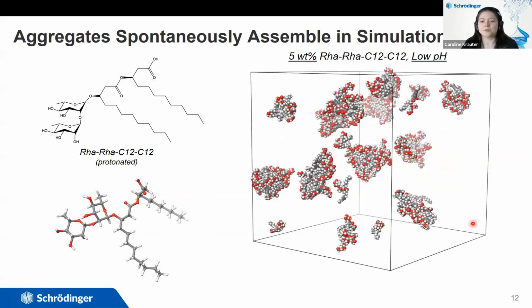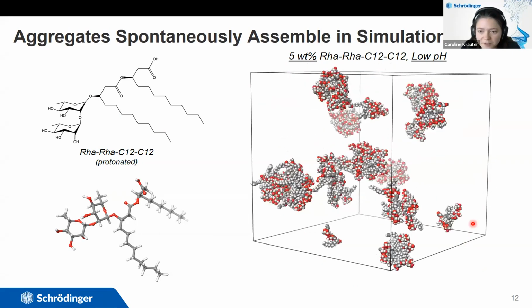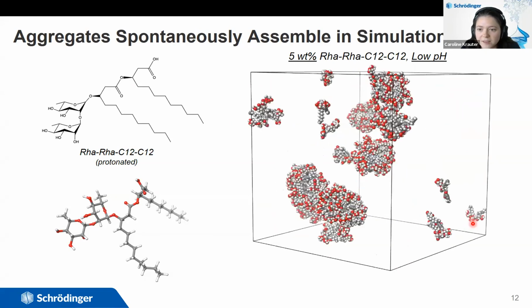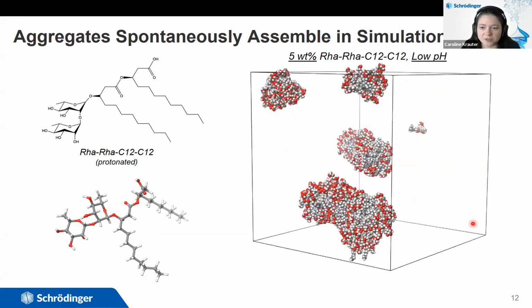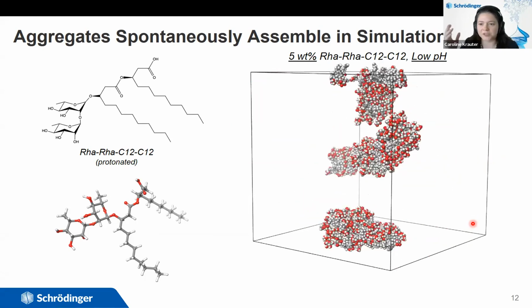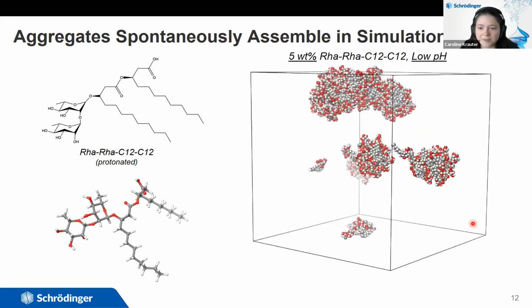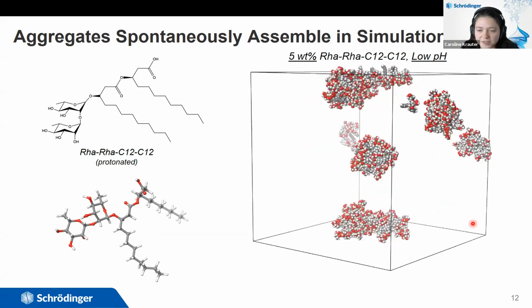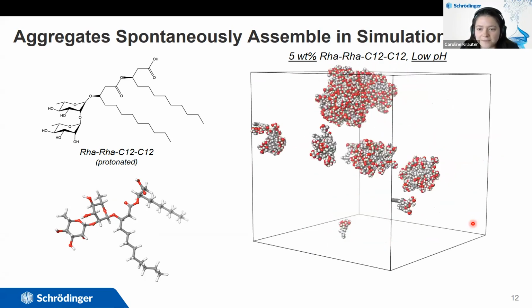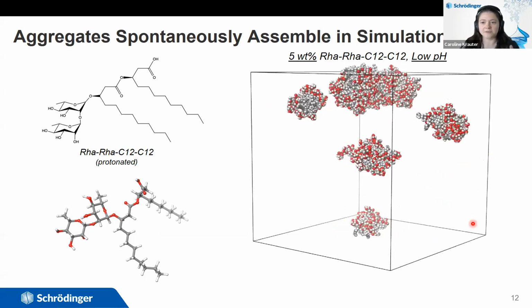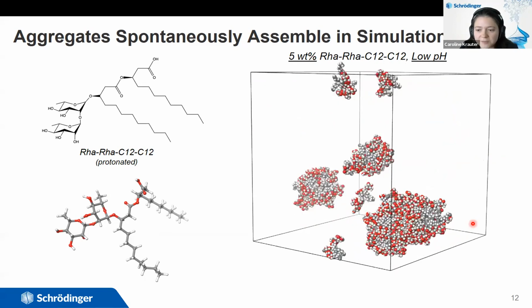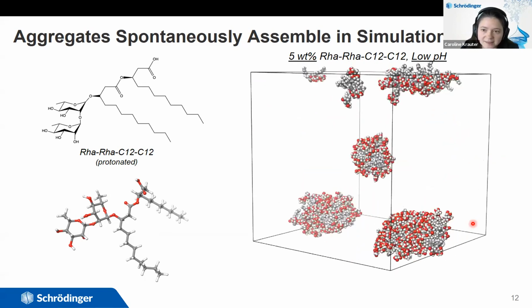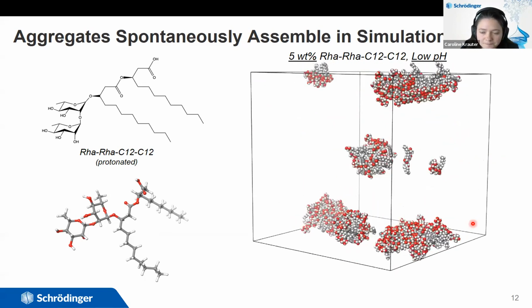We first run some equilibration protocols that we apply routinely: a series of Brownian relaxation, molecular dynamics at low temperature, then going up to high temperature. We equilibrate at constant pressure and constant temperature. From that equilibration, we average the volume of the simulation box, and then we run a 100 nanosecond simulation at constant volume.